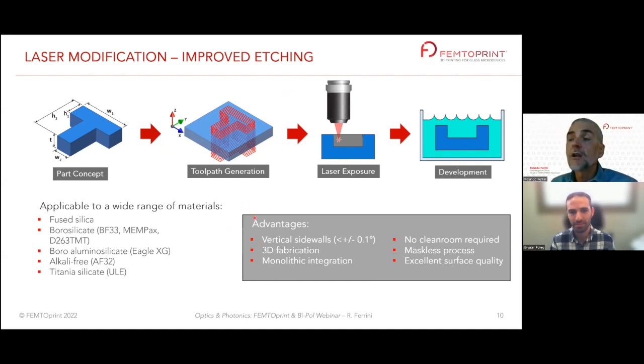So the advantages of our technology, for example in comparison to laser ablation, is that with laser ablation you generate a lot of defects at the surface that with our technology are removed in the second step process. Also, we have better control on the verticality of the sidewalls, better than 0.1 degrees. We can work the glass in fully 3 dimensions, for example, compared to other standard technologies like lithography. We can integrate functions. We don't need a clean room. We are maskless. And again, with a third step, we can get excellent surface quality.